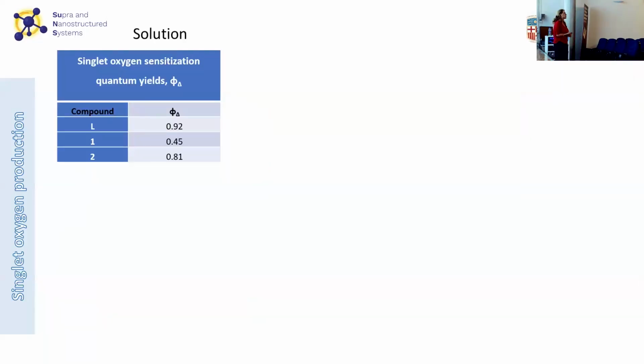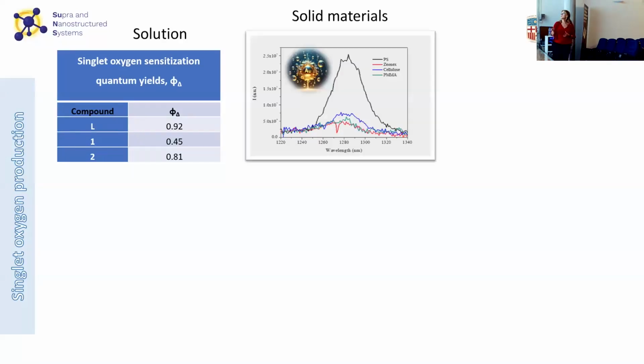But what happens regarding singlet oxygen? Well, we observed that all 3 molecules were quite good, minimum 50% of quantum yield on singlet oxygen production. So this was in solution, but as Andrea also synthesized these compounds in these organic matrices, we tried to measure the singlet oxygen also in the matrices. And what we observed is that, in fact, there is a clear winner, and this winner is the polystyrene. So it was not a direct correlation between having a polar and an apolar matrix, because if not, we should have polystyrene and Zeonex on one side and cellulose and PMMA on the other side. So it was just the polystyrene.